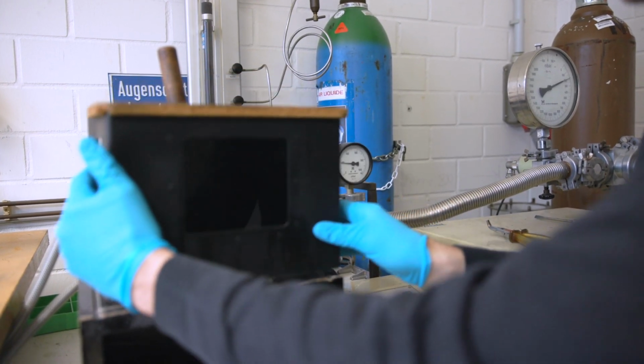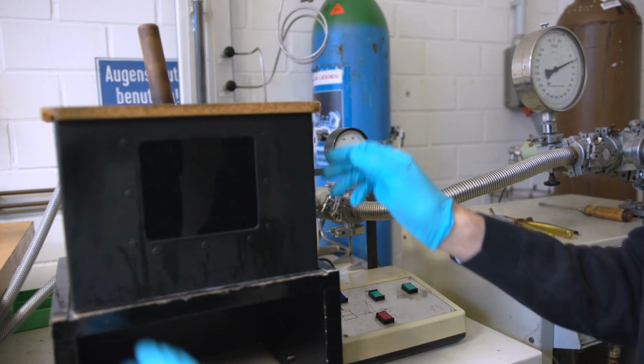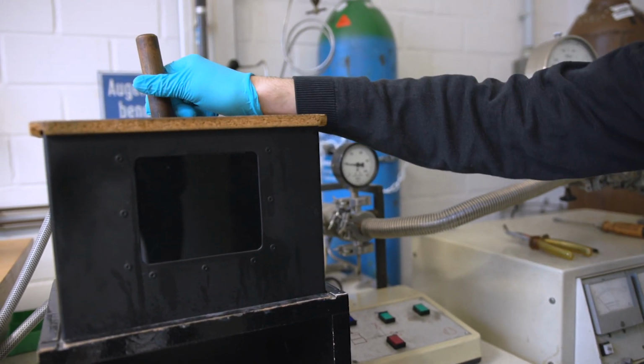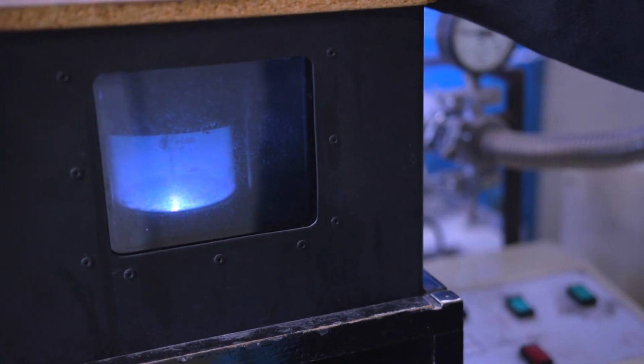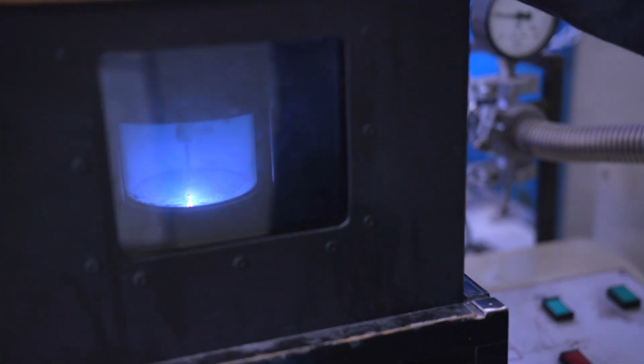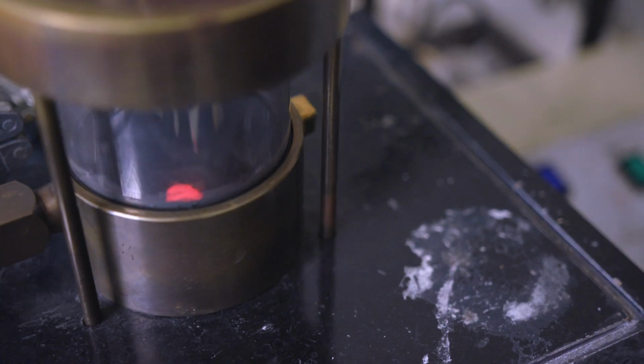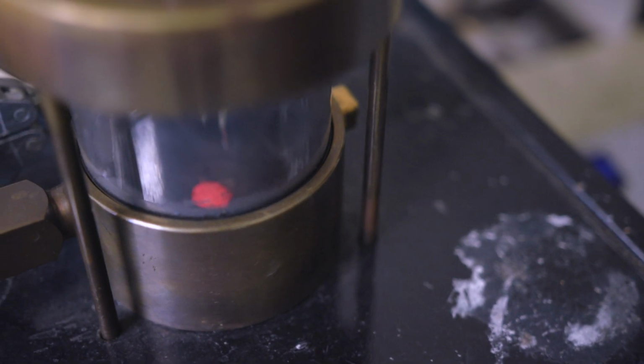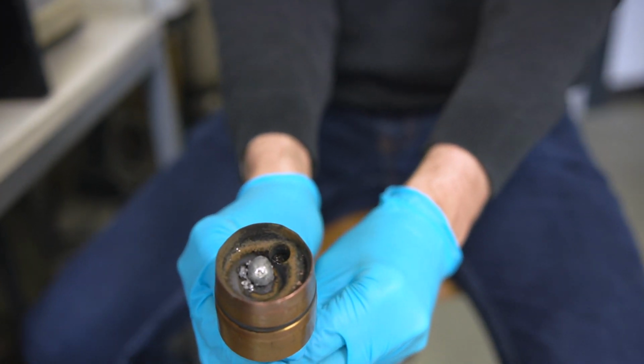It all begins with melting pure elements in an arc melter. An electric arc between a tungsten needle and a water-cooled copper crucible can easily reach temperatures above 2000 degrees C. Then, after a detailed structural characterization, we can investigate the magnetic properties.